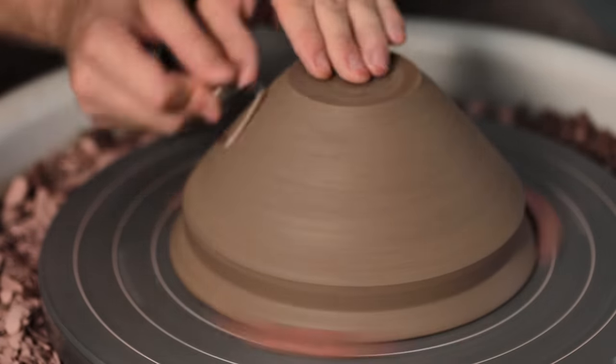Another difference I noticed when glazing all of these is how the clays they were thrown with affects how the glaze settles on them. Some of the stonewares will be more open than others, meaning they're more absorbent, whilst others will be more sealed, less absorbent, and the glaze coated over them will take longer to dry, resulting potentially in a less even surface, which means there's a knack for each for getting it right. The other thing to notice is just how cleanly the glaze flows off the bodies that are smoother, on the waxed portions. Whereas with this body, which is particularly coarse, the glaze really clings to the wax, which means I'll have to spend much more time tidying the pot up later, before it can be packed into the gas kiln and reduction fired.